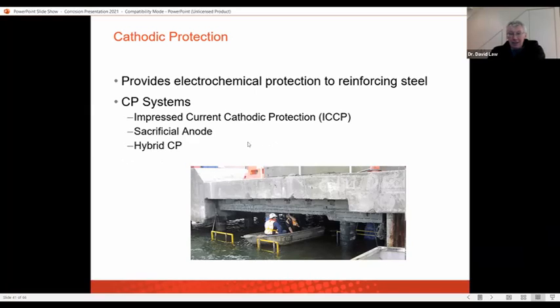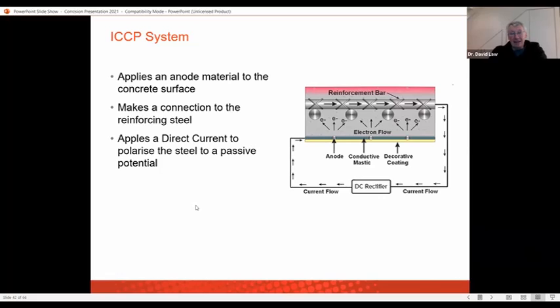And again, trying to understand when you will lose residual protection and how much current you're going to need and how long it lasts and how much residual protection you need will affect how long this hybrid will last and how much zinc you need to protect it, and the zones where you will perhaps not be able to apply hybrid, or whether you can apply it in all locations. And if you are applying it, how often you might need to replace any zinc that you've left to maintain the protection.